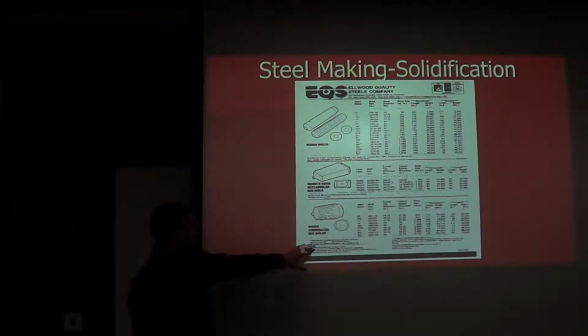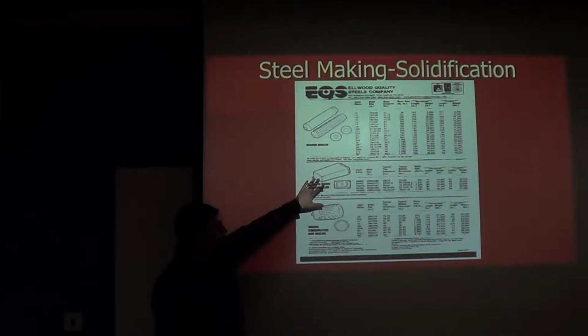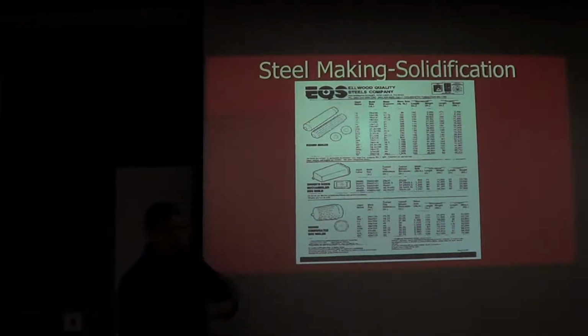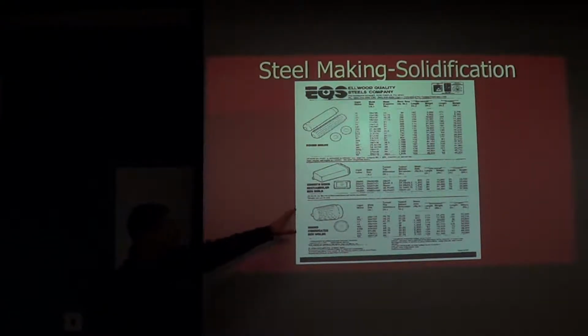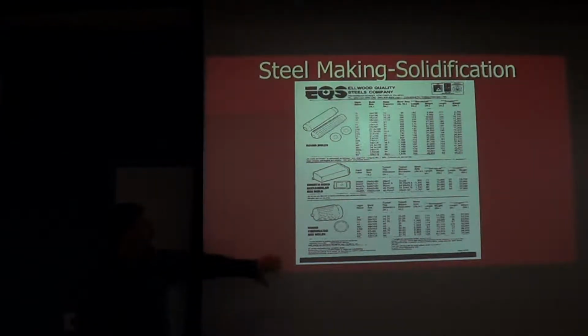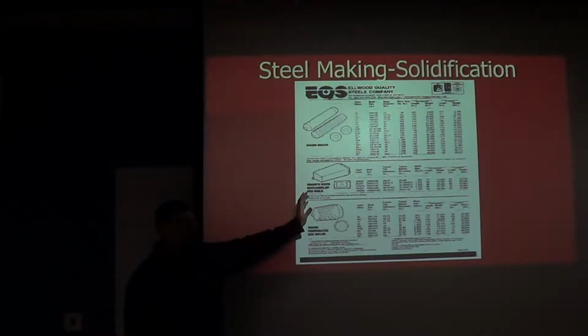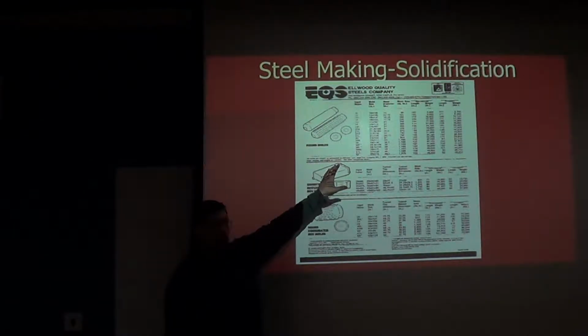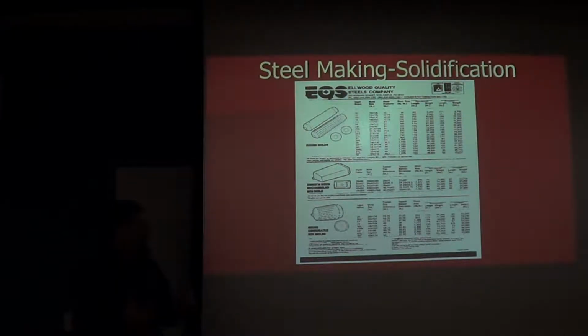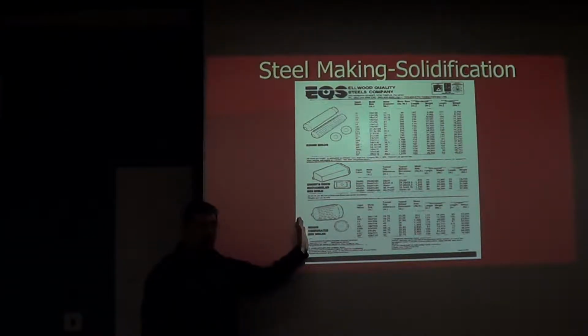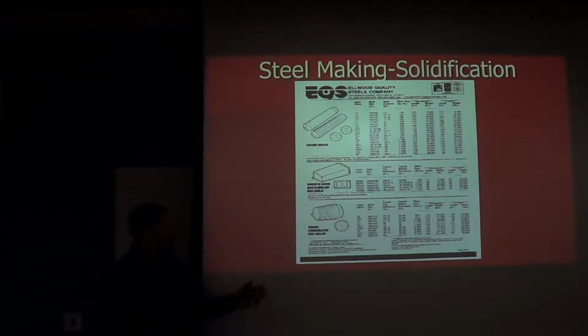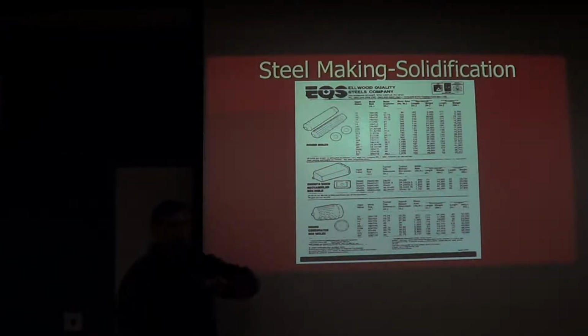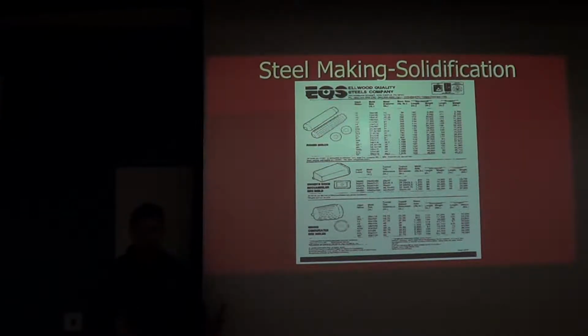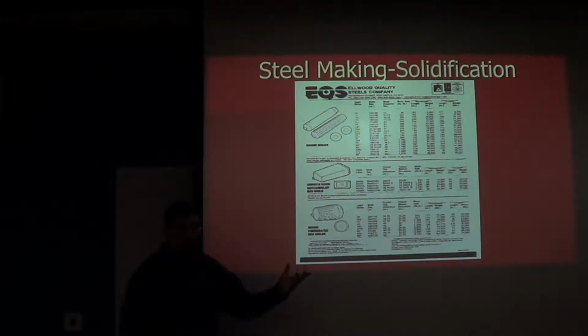Another type that we get are what are called big end up ingots. And these are available as rectangles or as tapered cylinders. The difference is that, and we'll actually get into it in a minute, I'll show you some schematics, but these two solidify from the bottom to the top, where these two solidify pretty uniformly along the whole length. That is significant because if you do have some small bits of non-metallic material, something that's solidifying directionally gives you more time for those little bits to float to the top. The top is something that we're always going to cut off and discard. So the result is that these two give us a little bit cleaner material, something that, depending on our customers' non-destructive evaluation requirements, we may need to use to meet them.